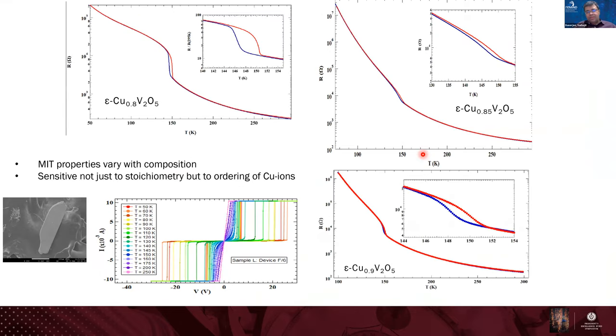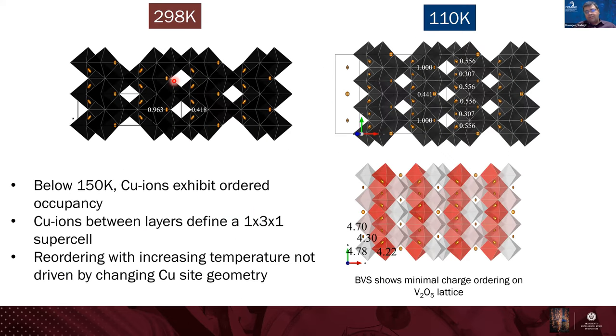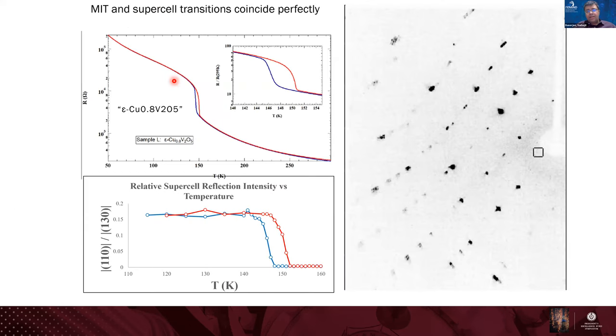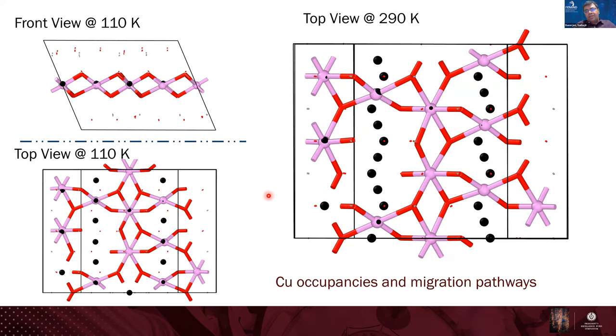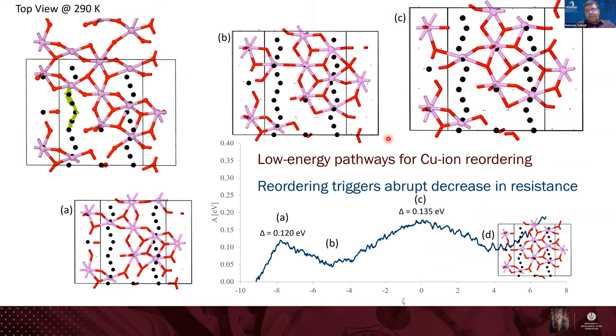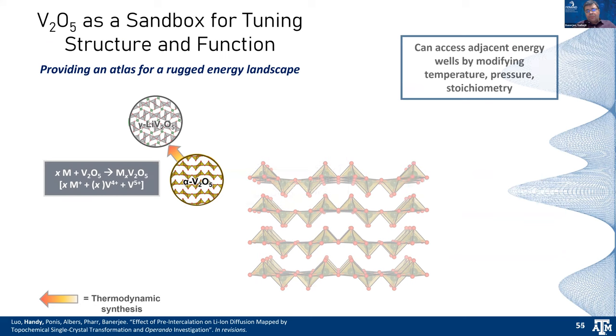And again, I think this is a perfect system for some beautiful measurements with our colleagues at APS, who have an amazing arsenal of tools. This is again a single crystal measurement, a pretty large transformation, 150 Kelvin or so. We can tune this transformation temperature a bit as well. Just before I end, we can actually map supercell reflections, and they decrease exactly coincident with the copper MIT as well. And we've got some AIMD simulations that essentially show that the copper has to migrate between two sites to disrupt the supercell ordering.